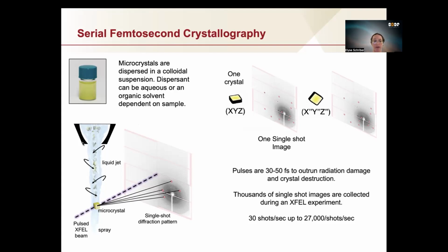So the way that SFX works is that you deliver this colloidal suspension to the interaction point of the X-ray, and you do this via liquid jets. So the jet velocity can actually be controlled such that you are delivering crystals at the same rate at which the X-rays are delivered. And the X-ray pulses can be delivered anywhere from 30 hertz, so 30 pulses per second, to 27,000 pulses per second at the high repetition rate facilities.